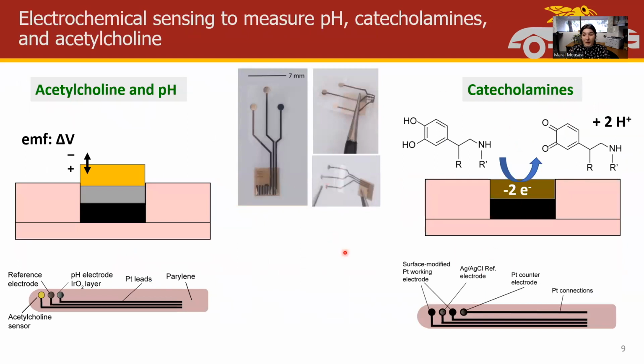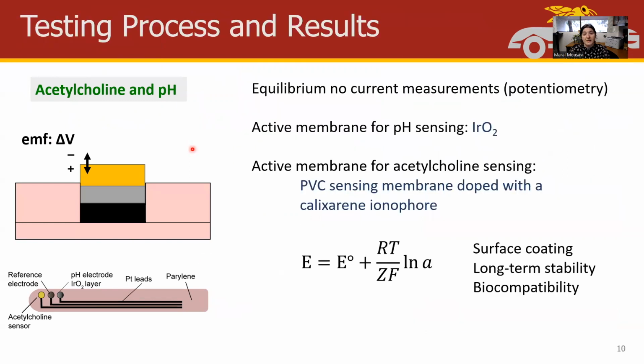So I told you a little bit about our catecholamine sensing module and how it functions. Basically, we utilize these parylene-based flexible electrodes, but through changing the coatings that we employ in the development of these sensors, we can now selectively detect pH and acetylcholine. The mechanism we use for sensing is slightly different, in that we monitor the surface potential instead of monitoring electrical current. In order to achieve selectivity, we utilize an active sensing membrane.